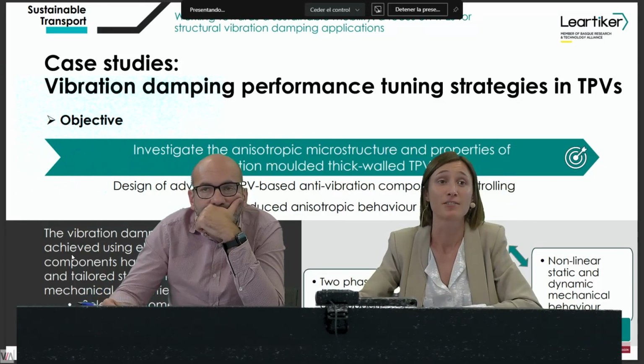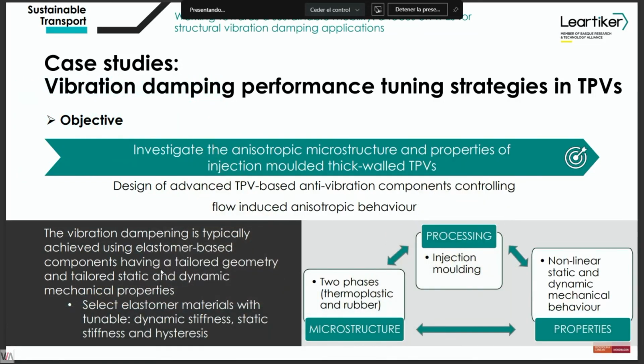Okay, so as I said, usually this vibration dampening is achieved by using elastomer-based components that have tailored geometry and tailored static and dynamic mechanical properties. So for that, the interesting thing would be to select elastomers with personalized or tunable dynamic stiffness, static stiffness, and also hysteresis. Hysteresis, why hysteresis? Because the hysteretic heating is also related with the fatigue or long-term dynamic mechanical behavior of this kind of material and products. So as I said, in this kind of materials, we have two phases. So we have a thermoplastic and a rubber. So we need to control the microstructure because this is going to influence then the final properties, which are this very non-linear, static, and dynamic mechanical behavior that you usually need to control also at product level.